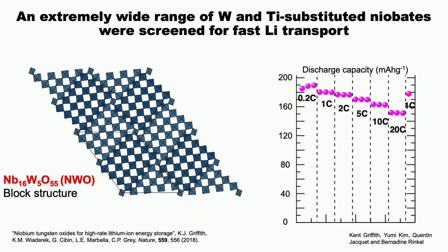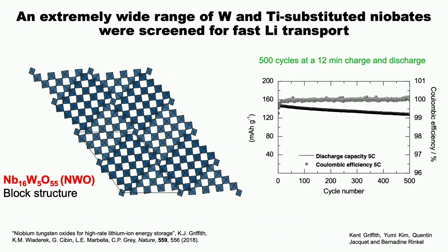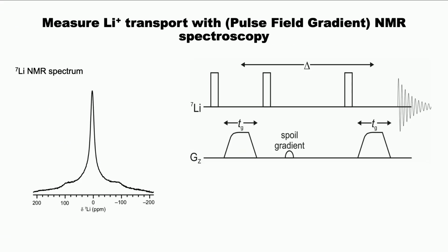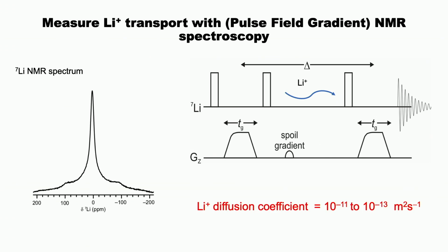And so with very little optimization, he was able to get a 20C rate. So 20C rate is a 3-minute charge. And the thing that's limiting that is not the material itself, it's the lithium metal that he's charging it against. And again, with very little optimization, he was able to get materials that were lasting for a very long time. And so then we can ask the question, well, why does it work? So one way of doing that is to do pulse field gradient spectroscopy. So you put a gradient across your material, you wait for the system to move, and then you quantify the echo, and you end up getting diffusion coefficients of about 10 to the minus 11 to 10 to the minus 13 meters squared per second.